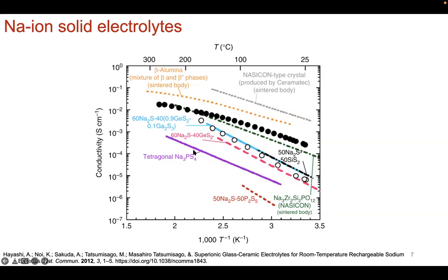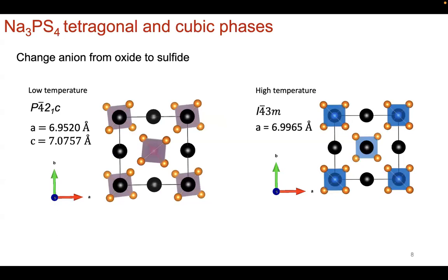Okay, and so this plot shows the tetragonal phase, and you can also have these glass ceramics, similarly to Li2S and P2S5, you can have Na2S and SiS2. You can have the NASICON type materials that have been sintered as well. You can have these germanium-based compounds. Of course, the only issue with using germanium is that it is so much more expensive than silicon. While it certainly increases the ion conductivity within a certain temperature range, you run into the same issues of manufacturing and scaling up these types of materials. So sodium thiophosphate has been pursued pretty heavily because the elemental components are relatively inexpensive. So that's what I'll focus on.